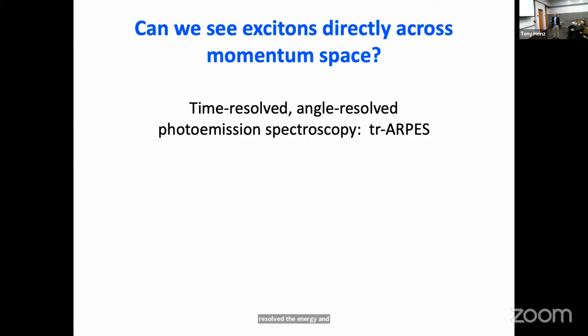And the question is, can we use this not to image the ground state of the material with the electrons completely relaxed, but to somehow image the excited states and the excitons? So this requires a little bit of a modification in the sense that you need to have an excited material. To have a reasonable level of excitation, you have to give it a good jolt of excitation, and you're not going to preserve a high level of excitation in steady state. So you want to do that with a pulse, and then you're going to want to use not angle-resolved photoemission spectroscopy, but time-resolved, angle-resolved photoemission spectroscopy.